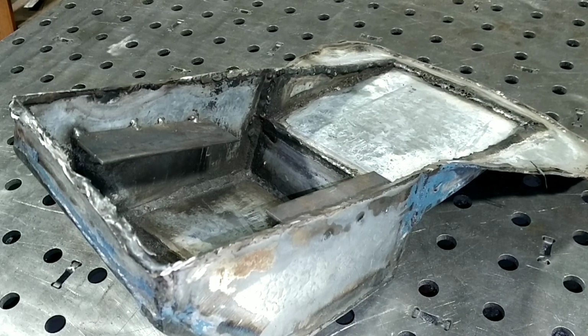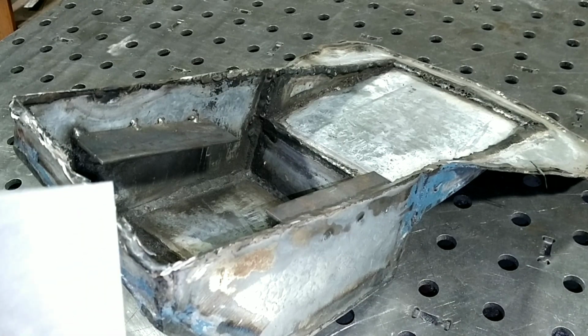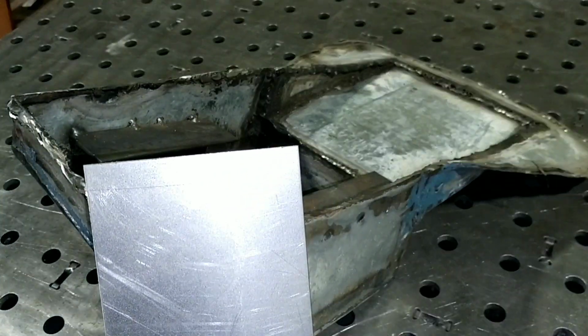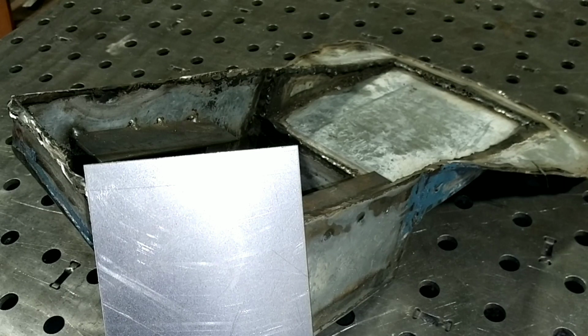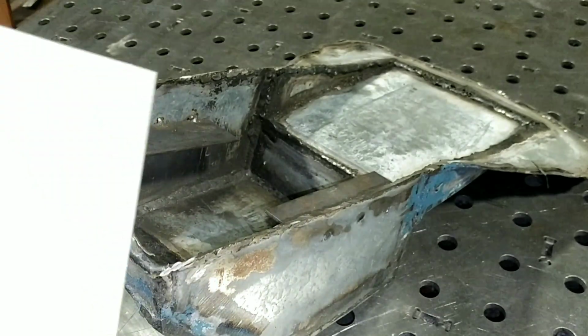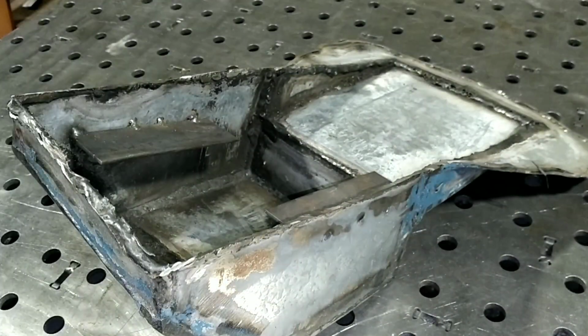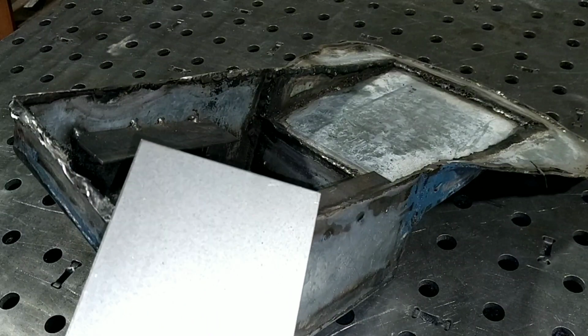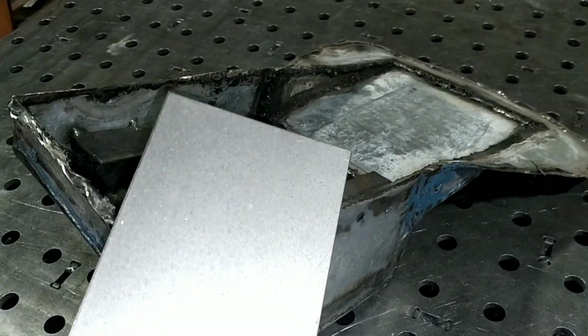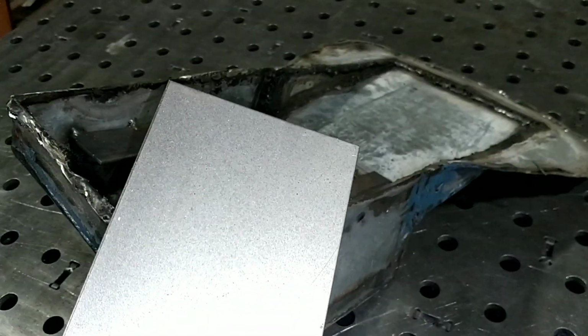You can grind it off, and the material underneath is exactly the same as what I would probably have used, which is this stuff, cold roll. Cold roll is the exact same material as hot rolled, except they wait till the material is cold, then they roll it out into sheet form, which breaks all that black oxide coating off. This stuff is really good to weld because it's pure and clean. There's no contaminants on it.